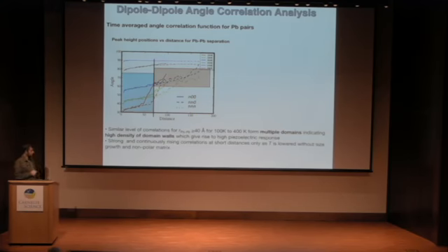Okay? And we can think of it essentially that the system forms a high density of domains with domain walls, and how strong the ferroelectricity is inside each domain differs with temperature. And we believe that this high density of domain walls, and these pretty small domain sizes, here about 6 nanometers, sometimes smaller, sometimes bigger, is what gives rise to the high piezoelectricity of relaxor ferroelectrics, because domain walls are very flexible and very responsive objects to electric field.